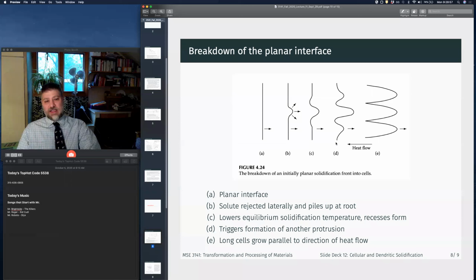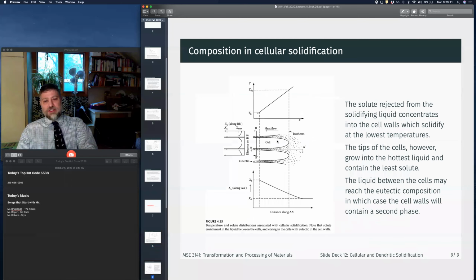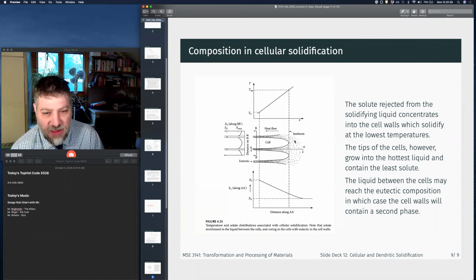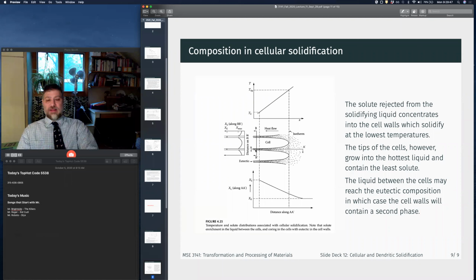And that composition gradient in X and Y leads to this cellular structure. As we reject solute into this interdendritic region, it's going to be a very different composition than what's in between, and this will typically form a eutectic. So in a binary phase diagram, the cells are alpha phase, and the region in between the cells is going to be a mixture of alpha and beta. We'll talk about that in more detail with the slides I put up last night on dendritic solidification, which we'll probably cover on Wednesday, and that'll be the last topic of examinable material.